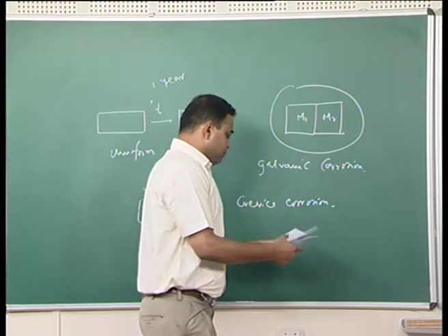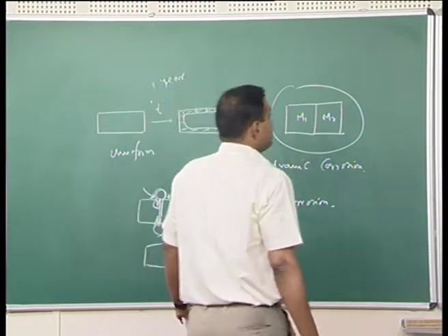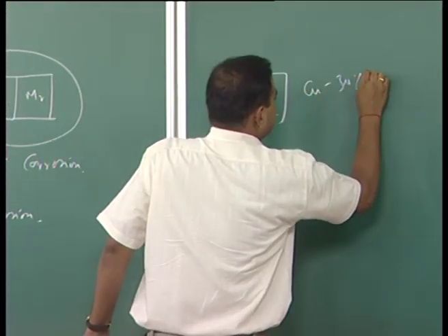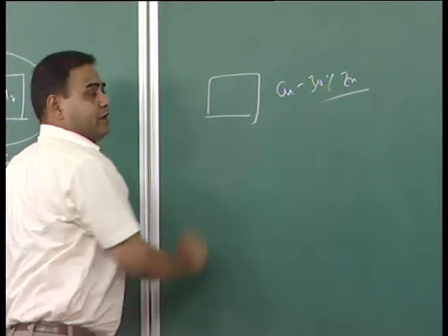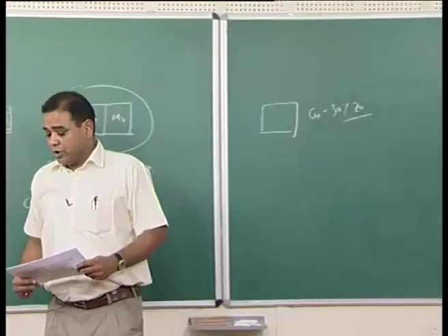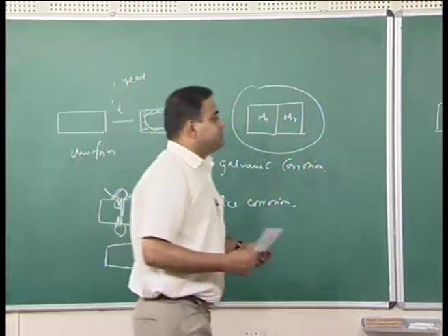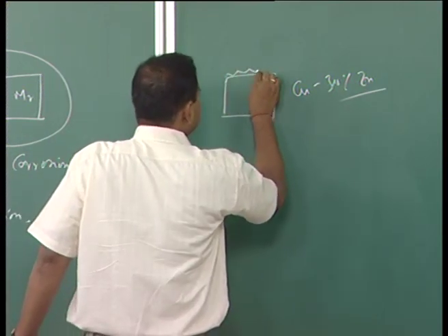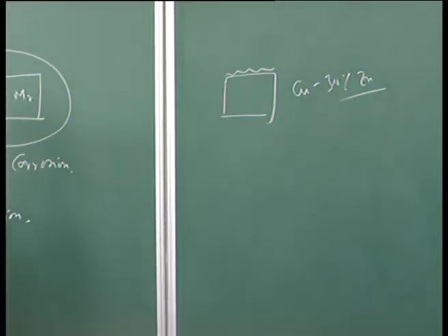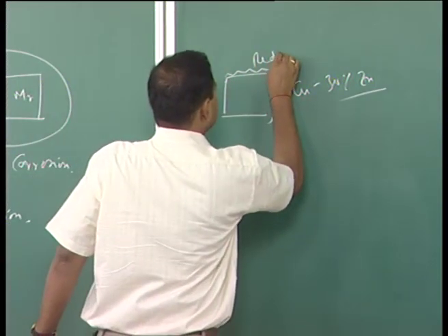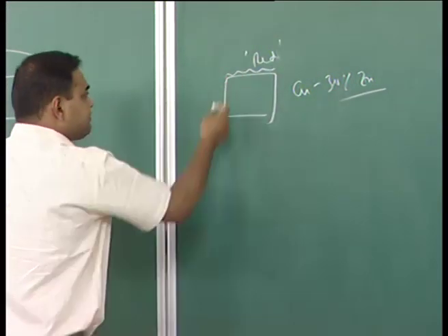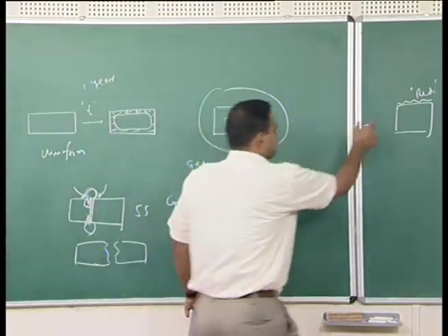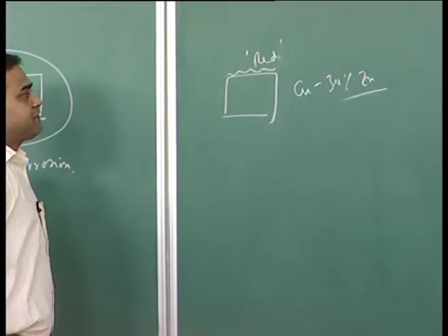Now you can also have, let's say, a brass, copper 30% zinc. If you expose this alloy to potable water, after some time, let's say 1 year or so, you will see that the surface is becoming reddish in color. This red color is coming because, if you study the top surface, copper is depositing on it.